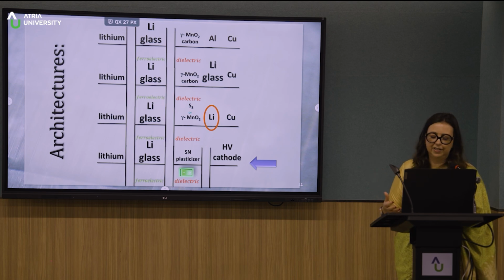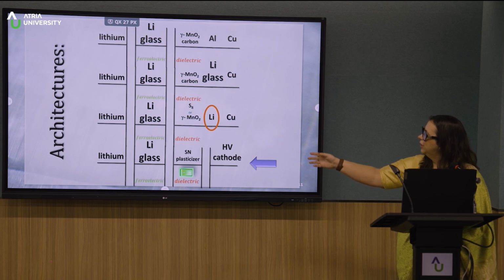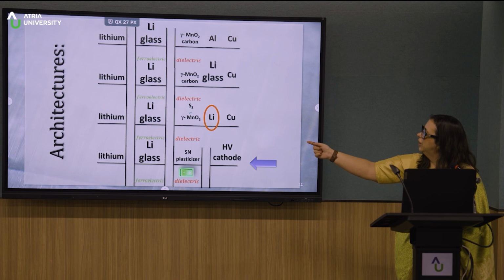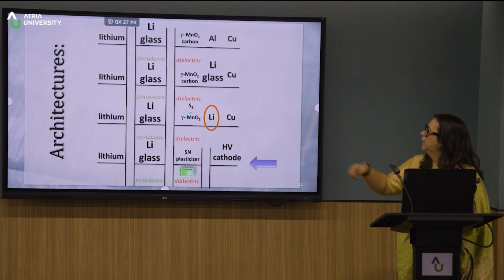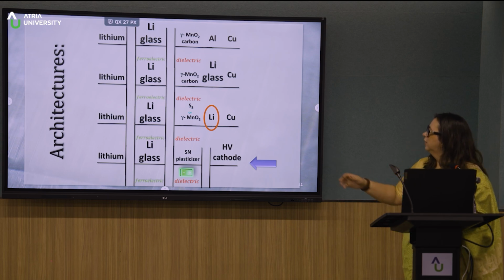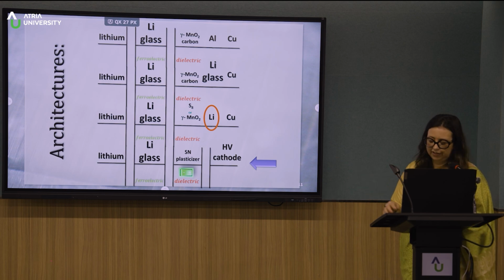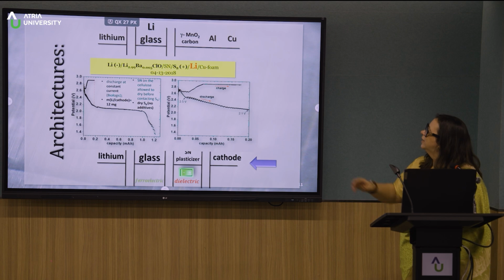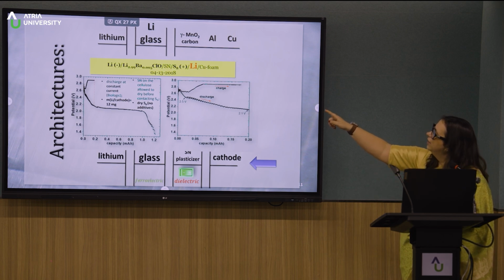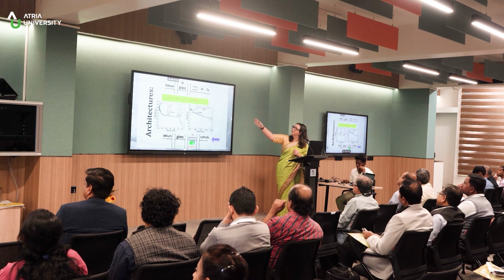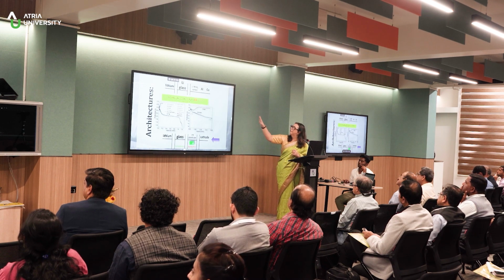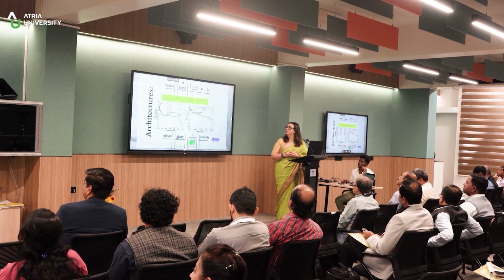But we need lithium to move in the cell, and that's where the ferroelectric material enters with a lot of lithium. And the electrolyte will replenish the lithium and the electrons in the lithium in the negative electrode. So that's how it works. This cell works. So here it is. This is the charge of a cell that contains lithium, the electrolyte, and the Sn, which is the on-off, sulfur, and lithium again in copper foam. So we put the Sn as the plasticizer so that we were sure that the lithium will not go anywhere from the positive electrode side.